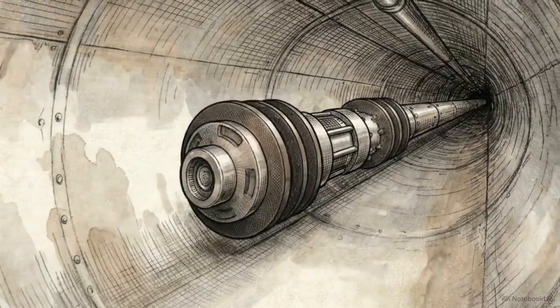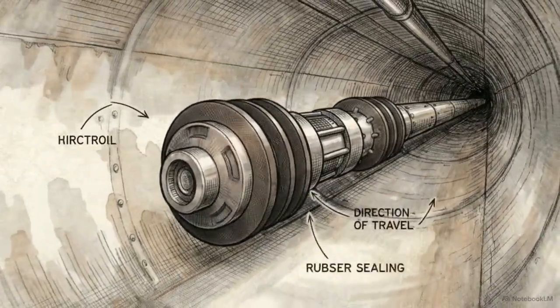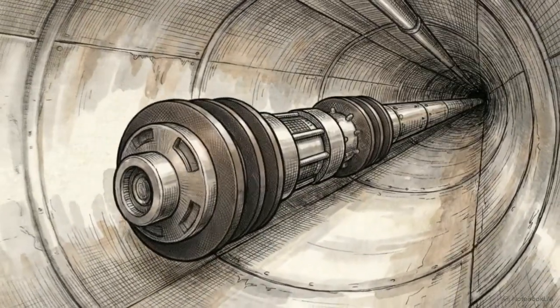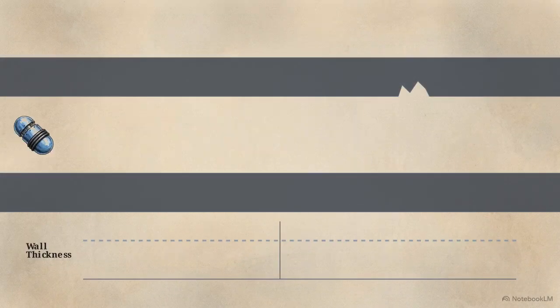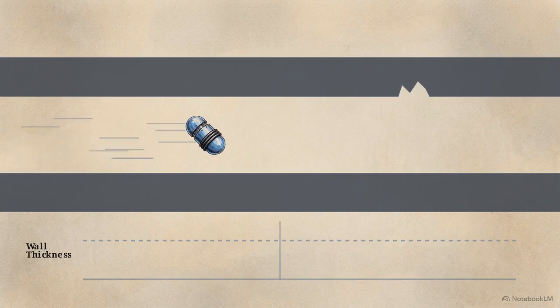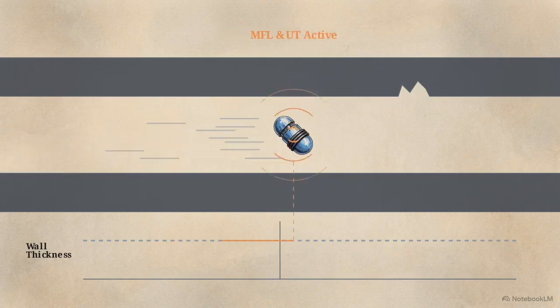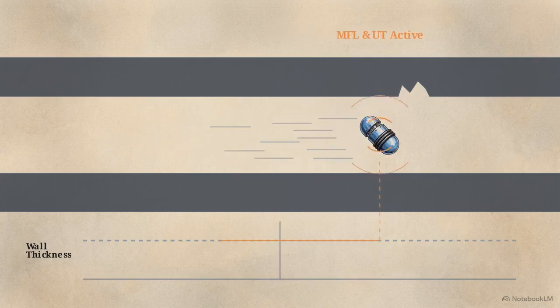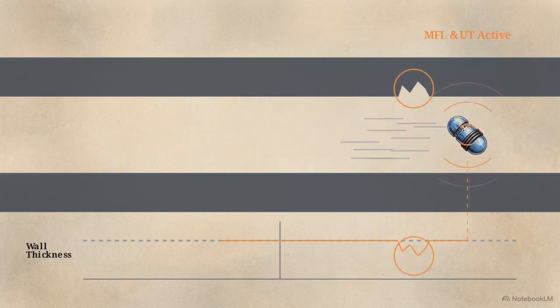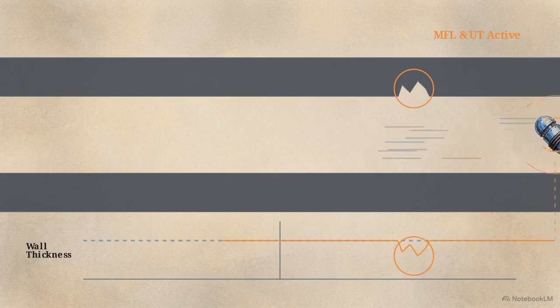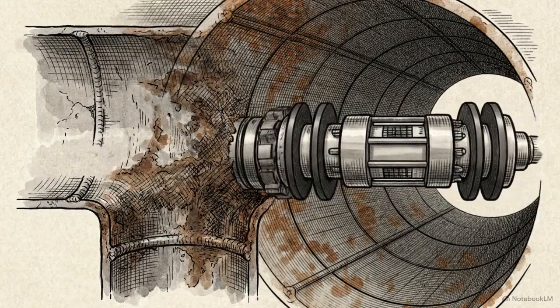To verify the structural integrity of a pipeline from the inside out, the industry relies on inline inspection, or ILI. These inspections use tools called smart pigs, which travel through the active flow of the pipe. As they move, they use magnetic flux leakage and ultrasonic testing to continuously map the internal wall thickness and detect metal loss. But this direct method has a strict physical limit.